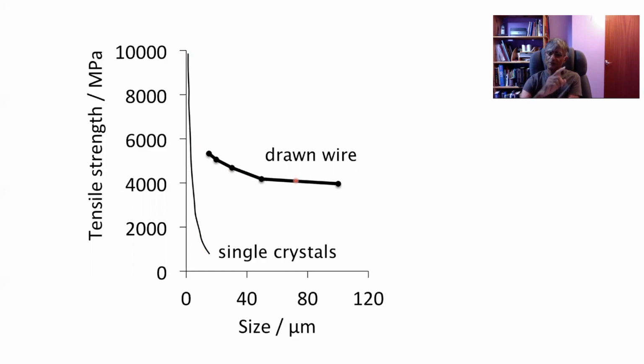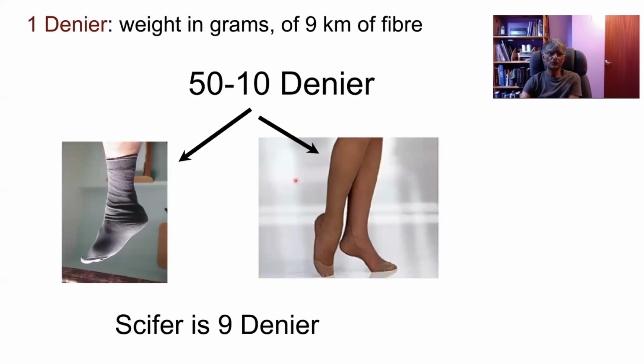The problem is that when you have to put in so much deformation, you end up with an extremely thin wire. And just to illustrate how thin that is, if you look at the men's socks or women's stockings, the definition of that thread is in terms of a denier, where a denier is the weight in grams of 9 kilometers of fiber. And women's stockings tend to be about 10 denier and men's socks about 50 denier. Now, Scifer, the steel wire that I just explained, is 9 denier. So it's finer than the thread in women's stockings.